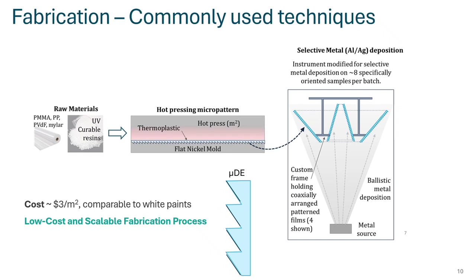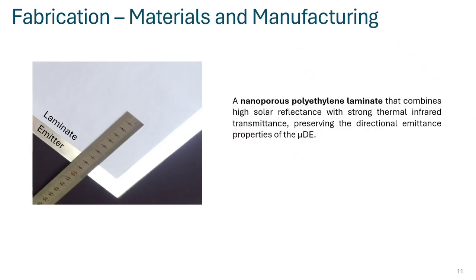Overall, we present and propose a low-cost and scalable fabrication process with the cost of the directional emitter around $3 per square meter, which is comparable to the white paint you can find in e-commerce. However, thinking about the visible or solar spectrum, the design is not optimal yet, because from an aesthetic perspective, there is a mirror-like appearance from below due to the metallic facet, which is not desirable. And what's more, the solar radiation might significantly heat up the design as it is right now.